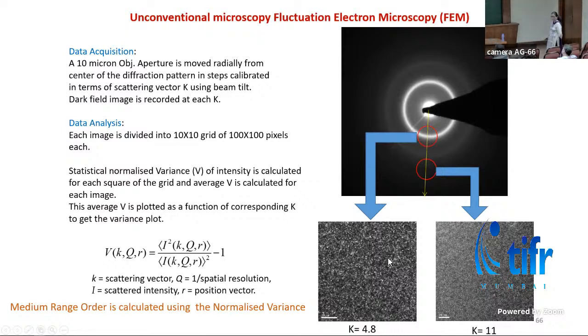the dark field images. Here we can see the dark field image corresponding to this bright ring, which shows a very nice speckle contrast. And if we calculate the variance of this image, that can tell us about the medium range order in the sample. So here, this is the diffraction pattern from this ring, which is very faint.